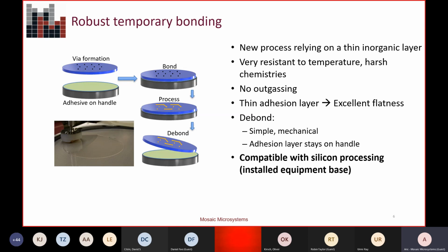There's other important implications where you can enable very thin fused silica products. So while display glasses can be manufactured in 100 microns thick or thinner, fused silica is manufactured much more like silicon. So you have more of a boule, a wire saw, and a grind and polish process. That makes it very difficult to get below 300 microns.